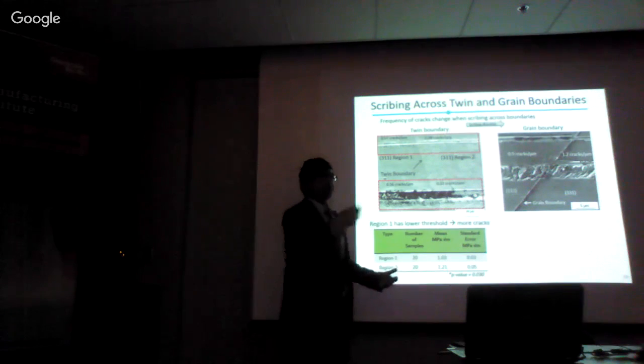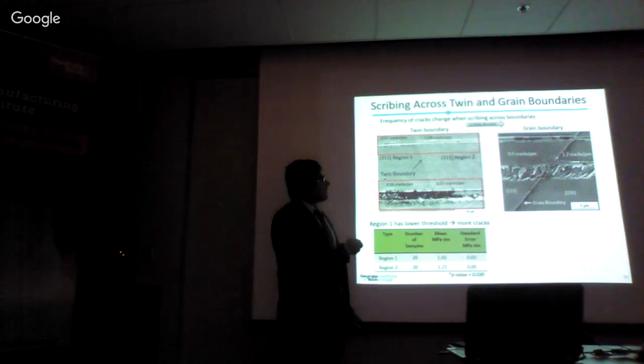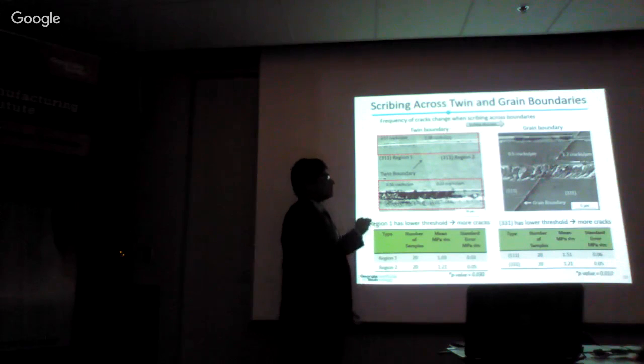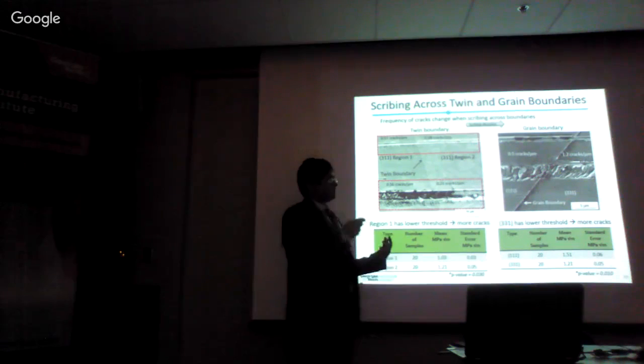And this we see is true even for grain boundary. This was at another part of scribing across the twin and grain boundaries, where we found that while scribing across this 111 grain and 331 grain separated by this grain boundary, the number of cracks per unit micron, or the frequency of cracks, was smaller here. On the right-hand side, 331 gave a higher frequency, or higher number of cracks per unit micron of the scribed length. And we found here also 331 had lower threshold, or lower fracture toughness, meaning it's easier to crack 331 compared to 111.